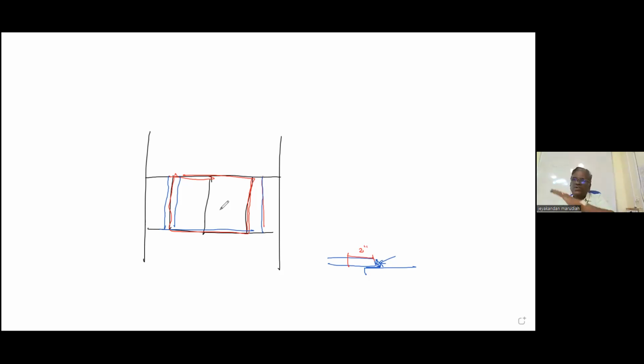Any lap joint, you have to deseam it, or cut 2 inch away from the joint. The only thing in the butt weld, if you are cutting on the joint and the thickness is less than half an inch, you can cut exactly on the weld and remove the weld. But if it is more than half an inch, it is not only the weld; you have to cut the weld plus the heat affected zone also.